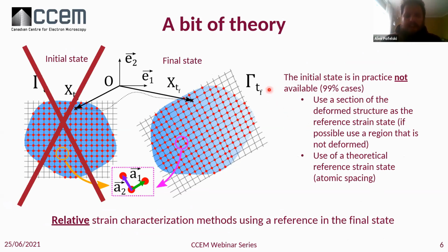Having that in mind, we have certain problems when we talk about strain in the TEM. Usually the first problem that we have is that we don't have access to the initial state. That is true when, for example, we have the sample at the end, already after all the processing, in terms of materials processing.